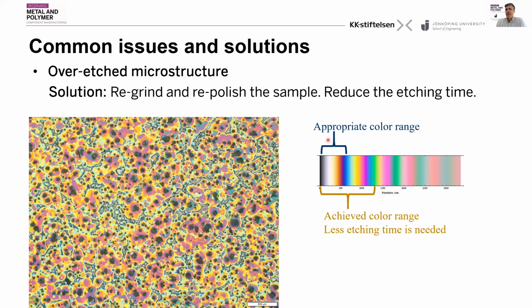The second problem that we can face during the etching is the opposite of the previous one. It's when we have an over-etched microstructure. Here in this image, we can see an over-etched microstructure, and the achieved color range is much larger than the appropriate color range, meaning that less etching time is needed. Unfortunately, when this happens, we must regrind and repolish the sample, which is time consuming, and also reduce the etching time in order to get the proper color range.